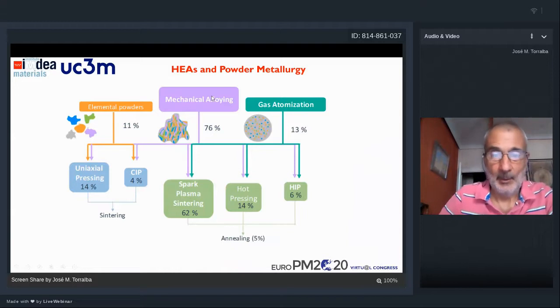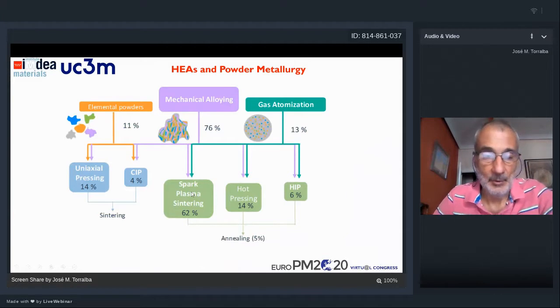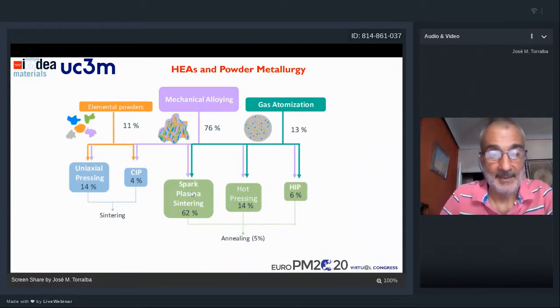When we use mechanical alloying, most of the time the consolidation method that we use to produce the final part is spark plasma sintering, and sometimes hot pressing, conventional hot pressing or hot isostatic pressing. But most of the time in the papers spark plasma sintering is used. At the end, sometimes we have to apply an annealing process in order to better control the final microstructure. By using elemental powders, we can also use conventional uniaxial pressing or cold isostatic pressing, followed by